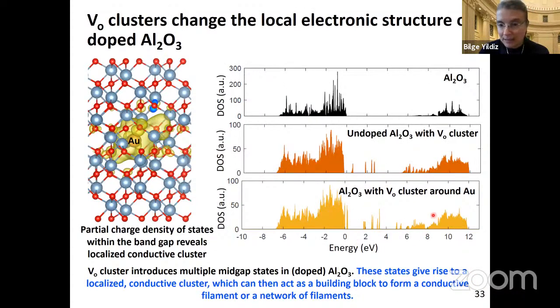And again, these clusters introduce a large number of in-gap states that can form the building blocks for conducting paths. So you have gold that favors to form and bind oxygen vacancy clusters, and they introduce in-gap states to provide the electronically conducting units for the network or for the filament.